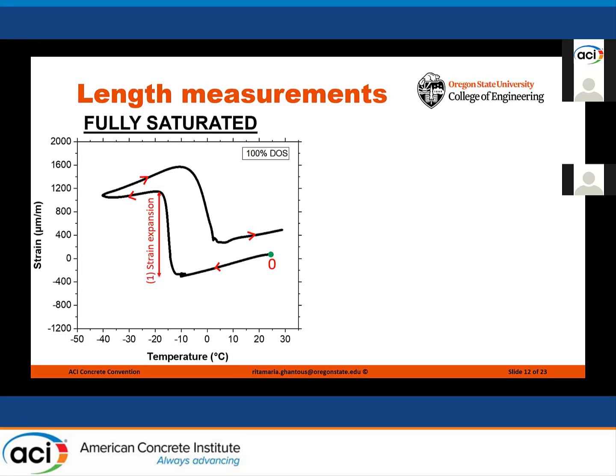Then, when the temperature increases, the length of the sample increases as well until the ice melts and the sample shows a reduction in length. This reduction is called strain reduction and can be determined by first finding the inflection point of the curve, then determining point A, which is the intersection between the vertical line passing through the inflection point and the tangent corresponding to the curve before the melting, and point B, which is the intersection between the vertical line passing through the inflection point and the tangent corresponding to the curve after the ice melting. Then the strain reduction is simply the difference between the strain measured at point A and the strain measured at point B.